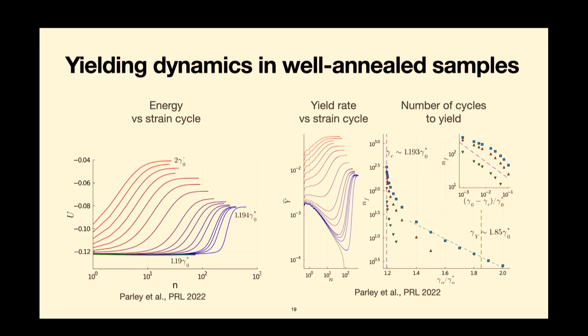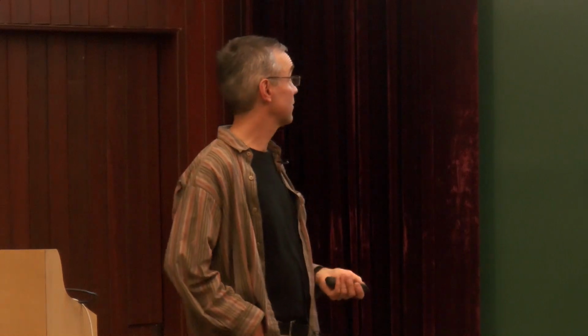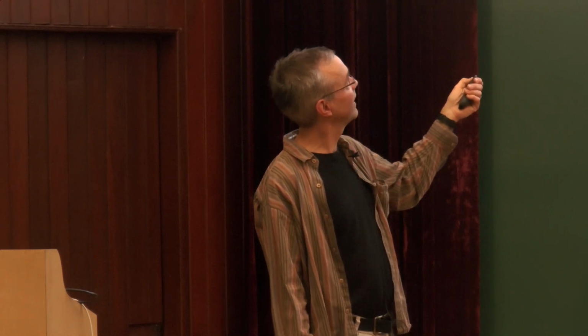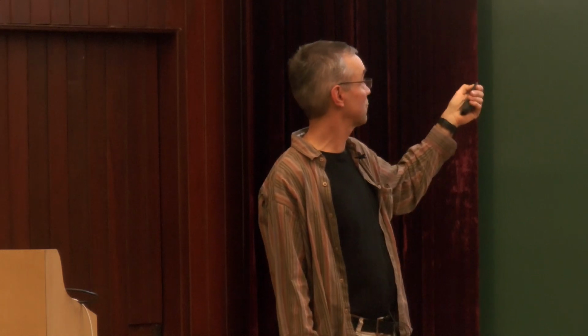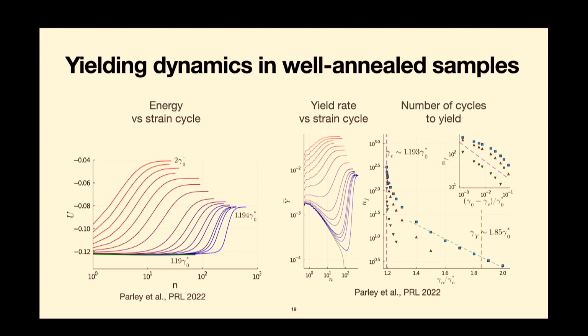So far I've only shown you the information about steady states. Now we're going to have a closer look and actually look at what happens as we really strain the samples over multiple strain cycles. So here's the energy as a function of strain cycle in a well annealed sample. And you see, depending on strain amplitude, here's a large strain amplitude. Here the energy goes up more or less from the word go. You reach a fluidized state. As you lower the strain amplitude and you repeat the experiment, the energy stays essentially constant for a long time, and then very late in the day, it starts to increase and reaches this fluidized state. And at a lower amplitude still, basically the energy just goes down, and then we cannot record it any further because the system is basically frozen, so it settles to a constant because that's the frozen state.